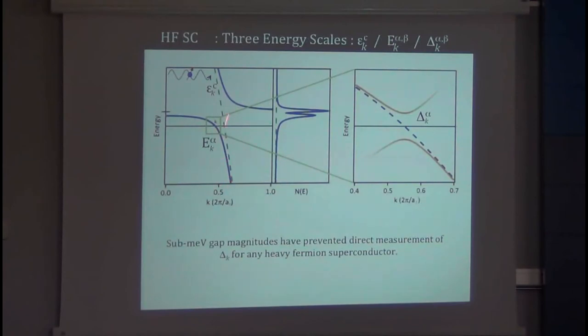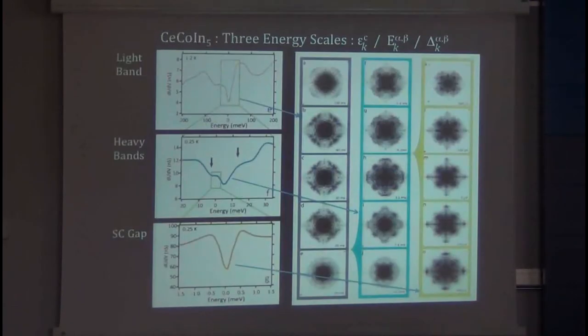You have to measure the light band. Then you have to measure the heavy bands. Finally, if the superconductivity appears where the heavy band crosses the chemical potential, a gap should appear in momentum space. So you have to measure three functions to understand how these materials work.